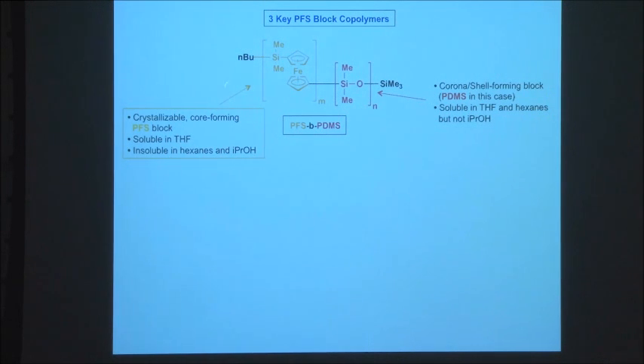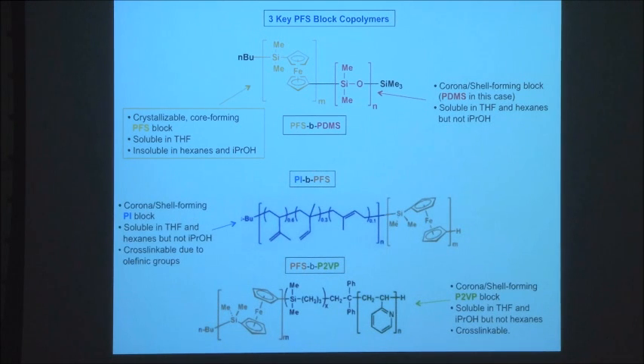So this is one of the polymers that we're going to talk about. Here's the dimethyl PFS block, which can crystallize. And this is the polydimethylsiloxane block here in red. And this will form the corona or shell. We're going to put these materials in a solvent that is selective for the polysiloxane block. So hexanes will dissolve the polysiloxane block, but the PFS block is insoluble. If you use THF, both blocks are soluble. So if you want to dissolve this material to give individual block copolymer macromolecules that are dissolved in the medium, you can use THF.